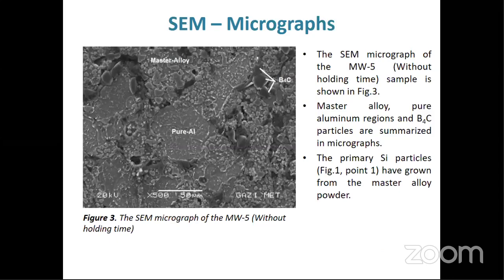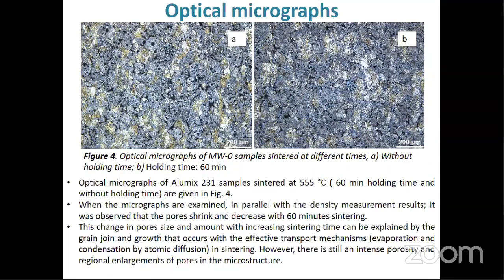The SEM micrograph of the MW5 without holding time sample is shown in figure 3. Master alloy, pure aluminum region, and boron carbide particles are summarized in the micrographs. The primary silicon particles have grown from the master alloy powder.